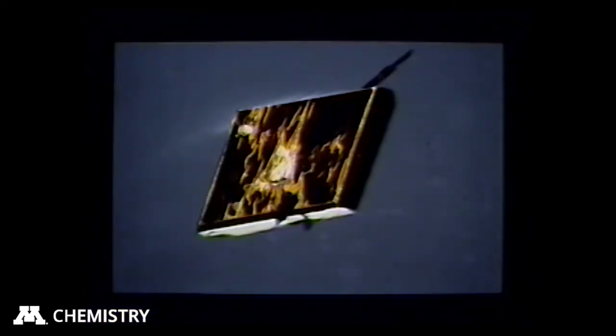The other characteristic is that at the end of the phase transformation, the crystal is a polycrystalline sample. So if you took an X-ray powder pattern of it, you would see powder lines. You wouldn't see diffraction spots. What that means is that there are a lot of tiny little crystallites of the product that are formed. But interestingly, the product crystal still has mechanical integrity, and you can pick it up and hold it in your hand and it doesn't just fall to pieces. It's very rare that these crystal reactions actually cause crystals to fall to pieces. They are going to change from transparent to opaque, however. That would be a typical change as these polycrystalline domains develop.